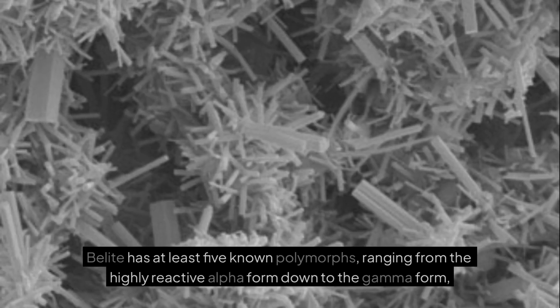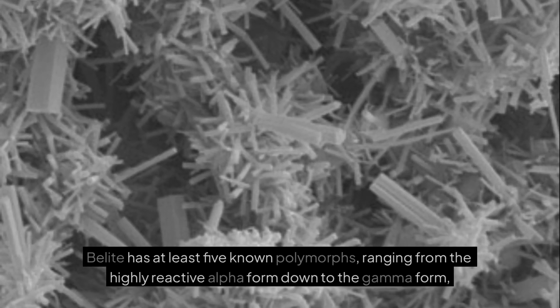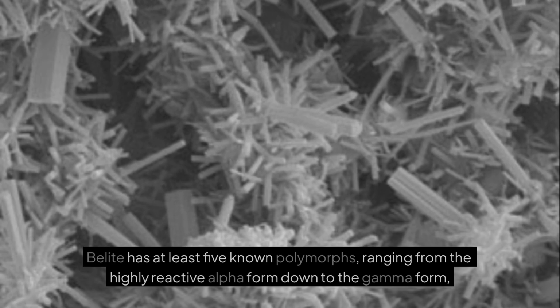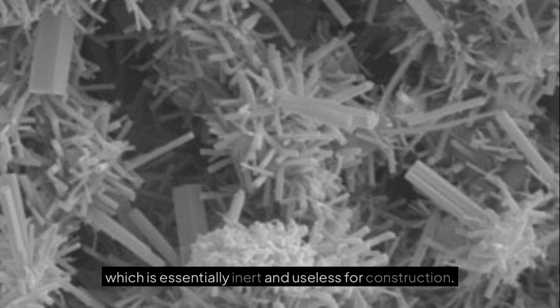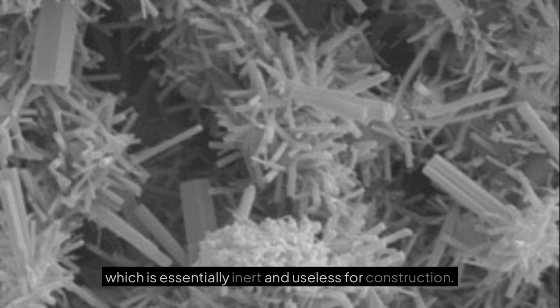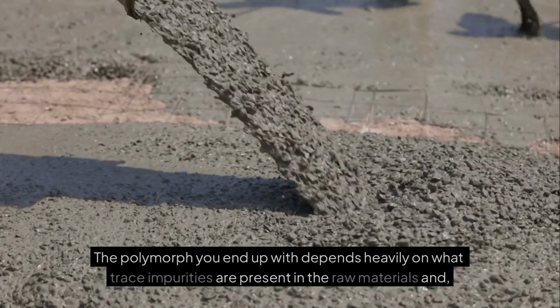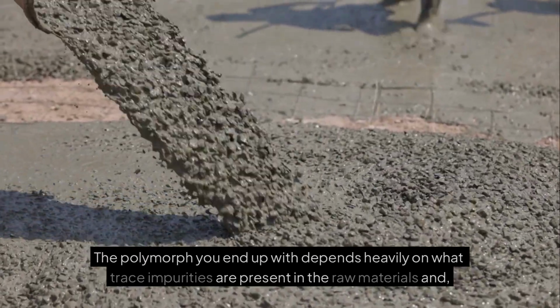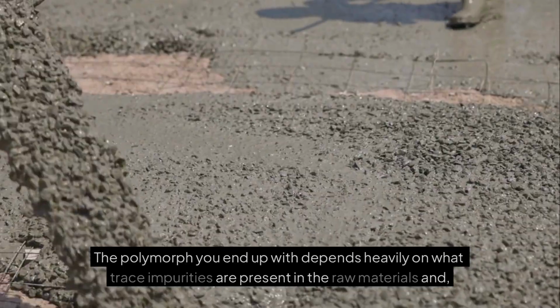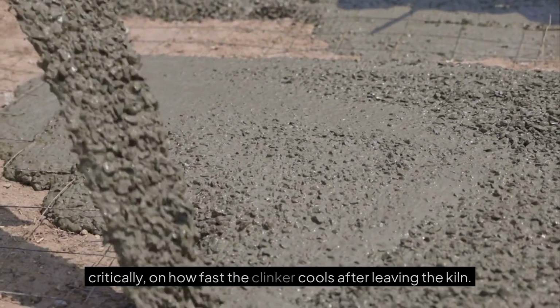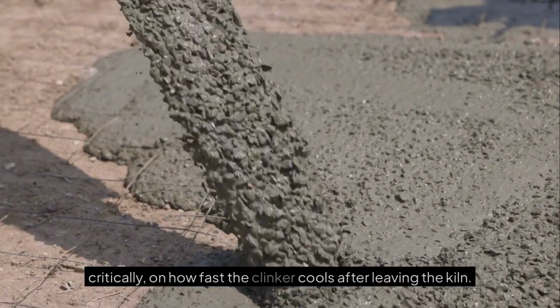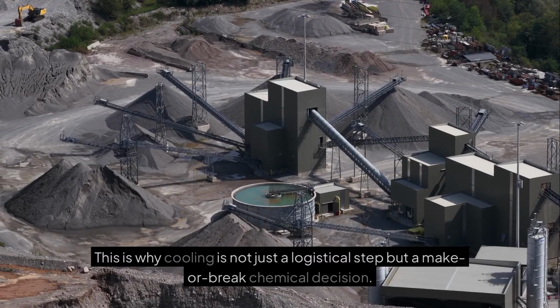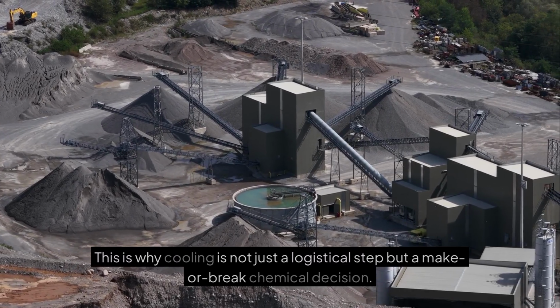Belite has at least 5 known polymorphs, ranging from the highly reactive alpha form down to the gamma form, which is essentially inert and useless for construction. The polymorph you end up with depends heavily on what trace impurities are present in the raw materials, and critically, on how fast the clinker cools after leaving the kiln. This is why cooling is not just a logistical step, but a make-or-break chemical decision.